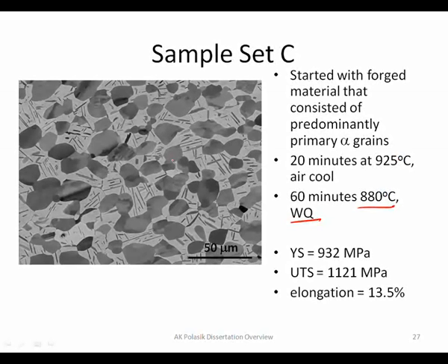And that affects the properties. It's going to have different properties. And dislocations are going to move through each one differently. And so sometimes, and this isn't actually beta and alpha, it's not alpha is harder than beta or stronger. So it's not really a precipitation issue. It's size scale, like variations in size scale of grain boundaries. And what ends up being the strengthening is more of a grain boundary strengthening mechanism that is that boundary between one phase and the other that inhibits dislocation motion.